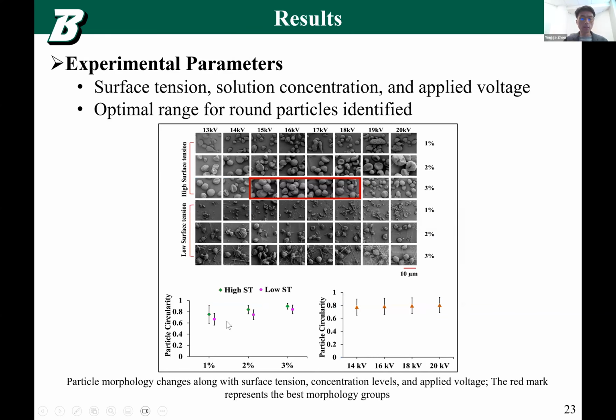And then we investigated the particle geometry and what kind of electrospinning or material properties can affect particle geometry. We want a round shape particle, right? We don't want broken particles. We don't want donut-shaped particles. We don't want fibers. As you can see here, we have some fibers. When we increase the material concentration and when we decrease the material surface tension, it looks like the surface tension, solution concentration, and voltage of the electrospray all have an effect on the particle circularity.